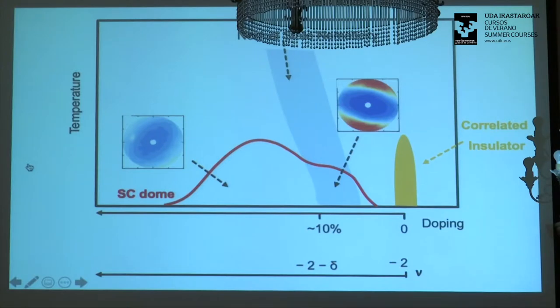There's always a coupling between electronic and structure that pins it. But once you reach a density for which the system has already chosen a strong direction in the normal state, stripes, charge order, some nematic direction in the normal state, the superconducting state aligns itself with that. And that's why it flips exactly when we go through that region. So this is sort of our understanding.